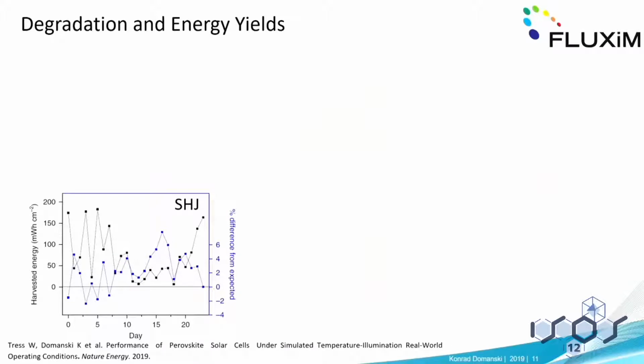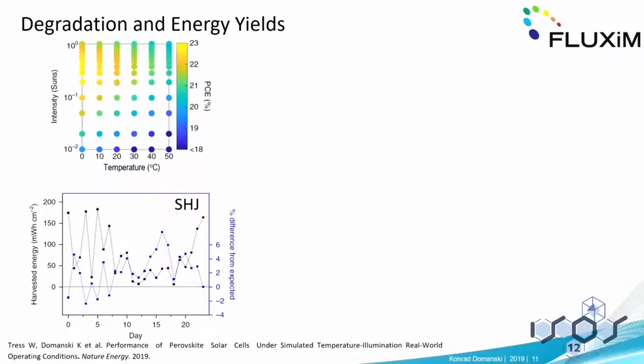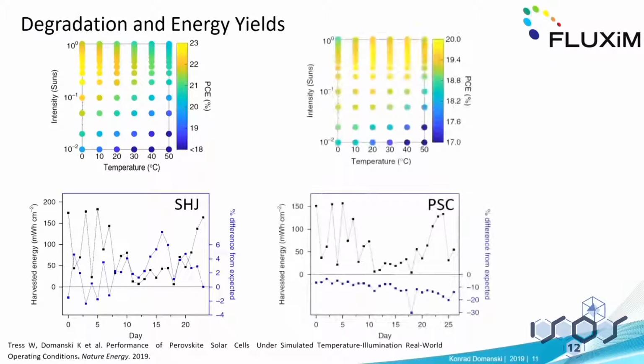So then let's look a little bit at the degradation. Because we did this initial characterization, we could predict how efficient our cell would be on each day, on average, because we know how it will respond to different temperature and illumination. So we plot here the blue curve, the difference between what we generated and what we expected to generate at the beginning. For silicon, you see that sometimes we generate a little bit less, sometimes more, no monotonic trend. For perovskite, the story is again different. We see that we consistently generate less and less as the experiment progresses. So we see some degradation.